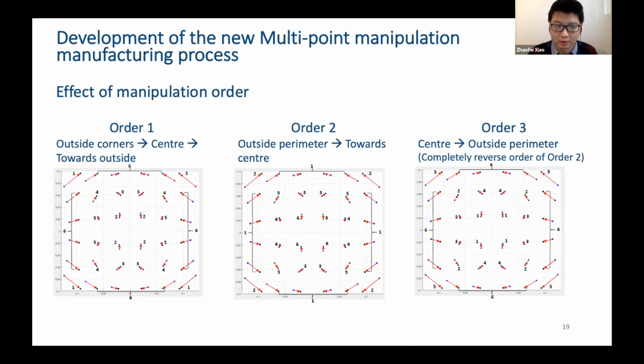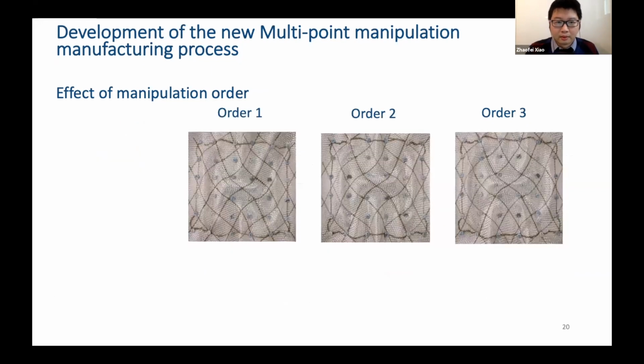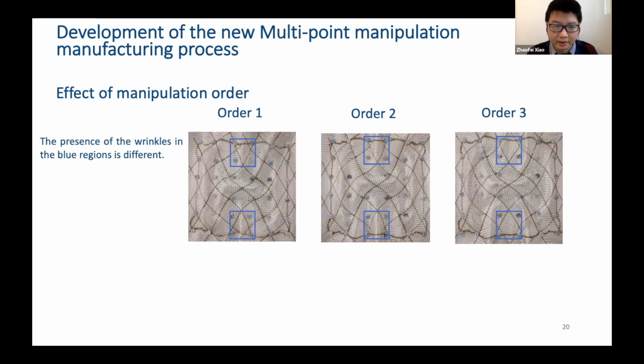We designed 3 orders. Order 1 is what we used to understand the repeatability, and in order 2 we start by manipulating some nodes around the perimeter first, and then move toward the nodes at the center. And order 3 is a complete reverse of order 2. So this time, we start by manipulating the nodes around the center, then move toward the outside. Now, if we compare the final steered pattern from the 3 orders, we can see in the blue regions, order 1 and order 2 have wrinkles, whereas order 3 doesn't have those kinds of wrinkles.